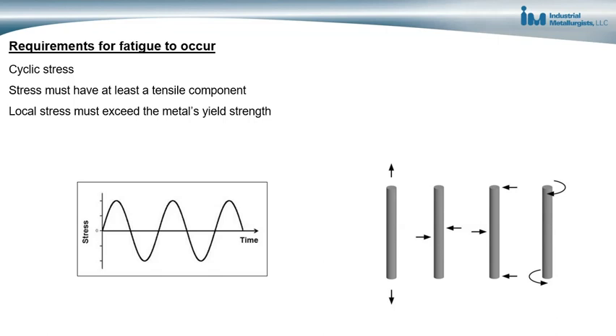So what's important to understand about fatigue is that we have formation of a crack at a stress that's less than the metal's nominal yield strength. And what happens is that at the localized area, the stress on the metal actually exceeds the metal's yield strength, but the stress on the entire piece of metal does not exceed the metal's yield strength. So the stress is exceeding the yield strength at a localized spot in the metal. But we don't see any deformation of the metal because the overall stress on the metal is less than the nominal yield strength of the metal.